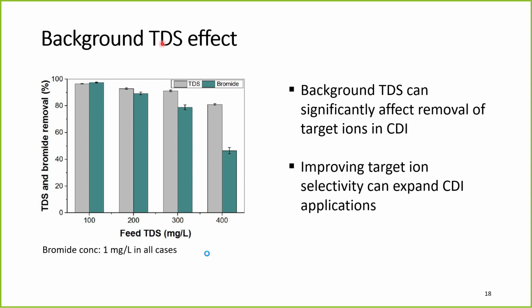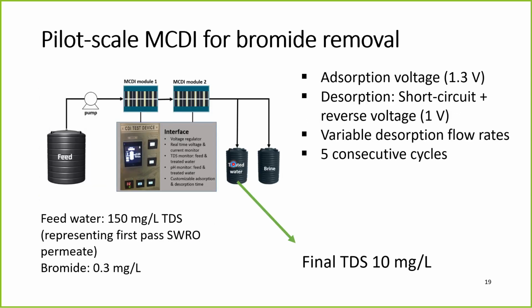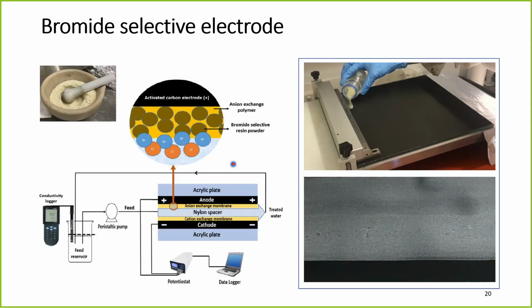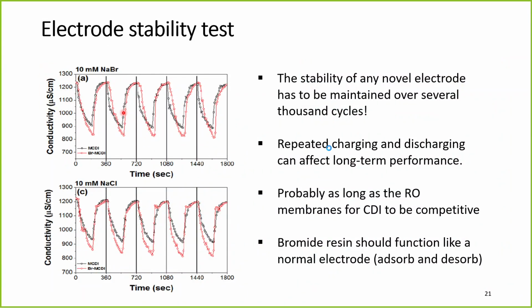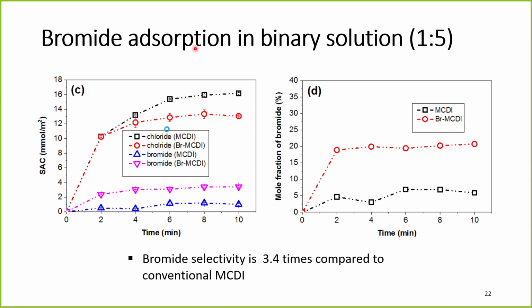So look at the TDS effect. When you have higher TDS, your bromide removal decreases when the background water is more salty. So we developed a way to specifically select bromide. We combined our activated carbon electrodes and put bromide selective resin on top of our ion exchange membrane. The anion exchange membrane polymer plus bromide selective resin were mixed together to produce this electrode with the bromide selective compound. Then we tested the stability, and this MCDI has very good stability. And look at the bromide adsorption.